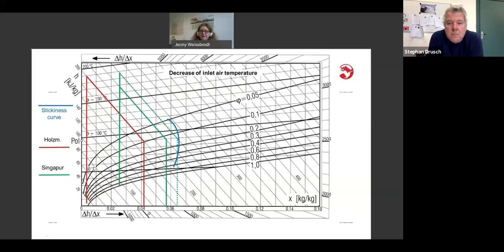Let's decrease the inlet air temperature. Okay, we heat it up this time to a temperature of 170 degrees C. And then we make our drying up to the outlet air temperature of 90 degrees C. And you see, you stay on the left side of the stickiness curve. You will have a free-flowing and dry powder. Of course, you have to drop your in-feed concentration a lot, which means your drying is a little bit slower. It will take 1 or 2 hours longer, but on the other hand, you don't have to clean up, and you have a constant quality of your powder, and it will come out as a powder and not as a plastic mass.